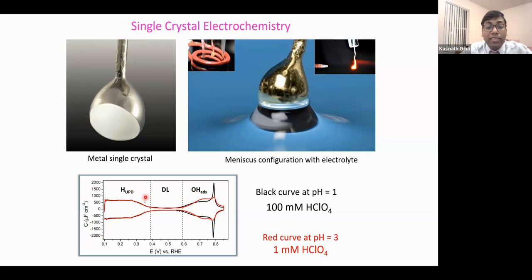And in the middle region, there is actually no specific adsorption happening. That's what we call the typical double layer region, where only ion charging and discharging happens. Basically, ions go close to the surface, and while discharging, ions go away from the surface. So this is a charging, discharging box, and we call it the double layer. Now, ideally, if we do low ionic strength measurements, we should see a minimum in this capacitance curve right here.